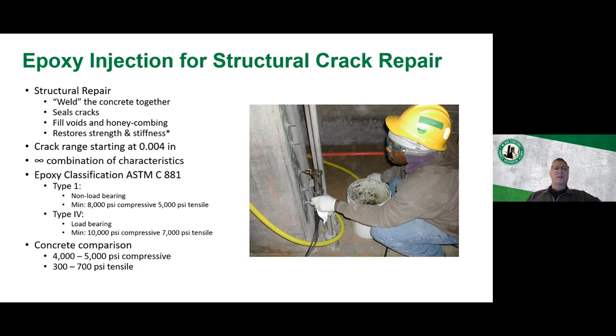And something I like to explain to people, especially why stiff epoxies are not very good for moving cracks, is concrete, your typical concrete, is 4 to 5,000 psi. So if you put a 10,000 psi epoxy resin between the two slabs of concrete and that concrete's moving, that epoxy is actually harder and stronger than the concrete around it. So as it moves and compresses up against it, that concrete will actually crack again. And so you'll have a crack next to a repaired crack because of that moving part.